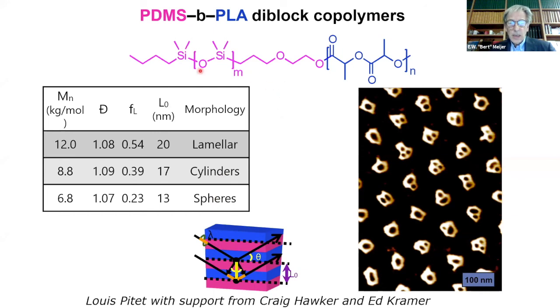So what Louis Pitet did, he synthesized a block copolymer of dimethyl siloxanes and lactic acid, having a very high chi value. He made them small with a low dispersity, and it follows all of the block copolymer work: lamellar, cylinders, and spheres. And then we take the one with cylinders and we put them into holes on a surface. And the hole here is about 50 nanometers. And what you see is that every hole has a different thing. It was a little bit surprising because it was the best possible polymer that you could make.